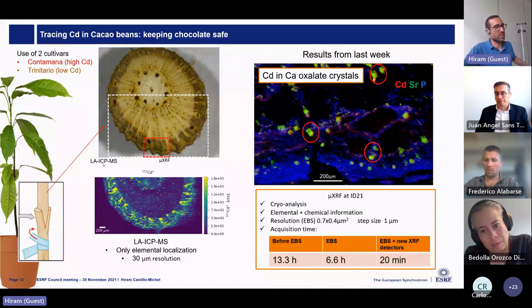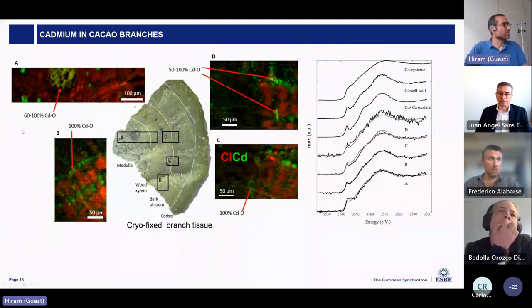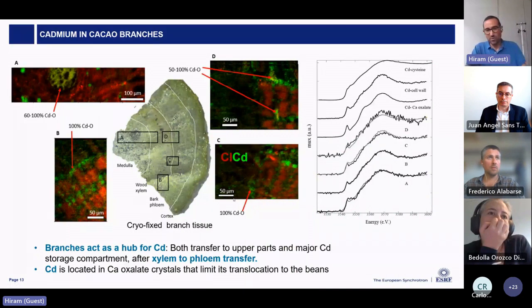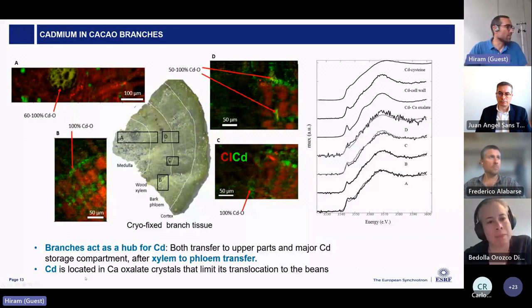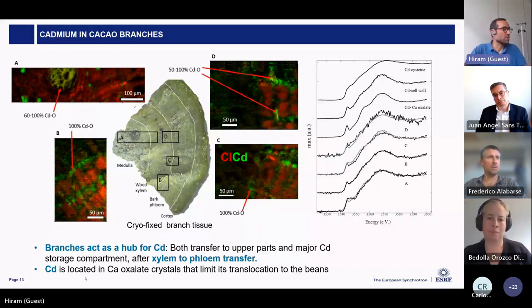And also we can perform this under cryogenic conditions, which is not the case for laser ablation. So here, I present a cryofixed branch tissue. Again, this is the section we prepared at the beamline, and you see the different maps. And the result is that the branches are the main hub for cadmium. They retain a lot of cadmium. There is transfer via xylem and phloem, from images that we performed in other tissues, and also other data that comes from other techniques. But one of the main results is that the cadmium is really fairly well colocalized with these calcium oxalate crystals, and we are trying to understand more or less why these crystals are produced and what their main role is. But for the time being, we believe this is actually quite a good thing, and more studies are ongoing.